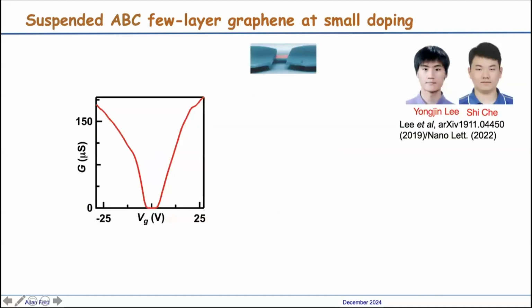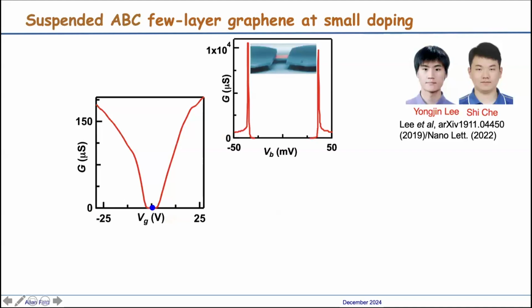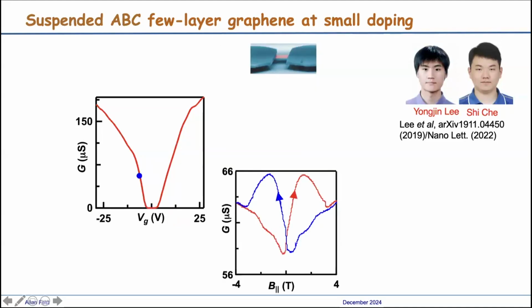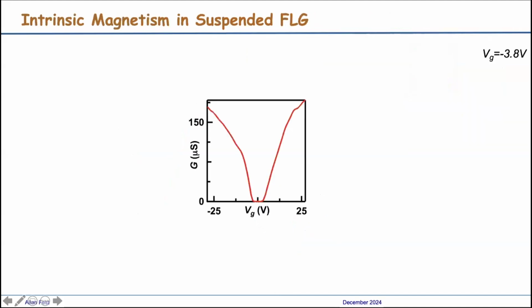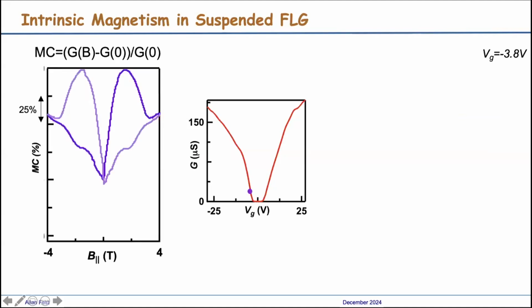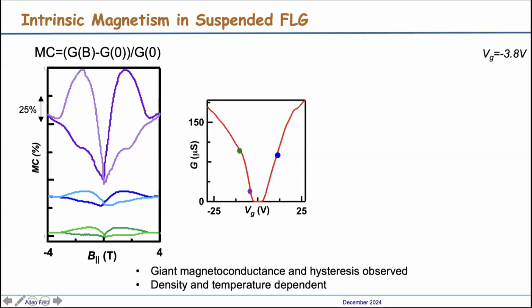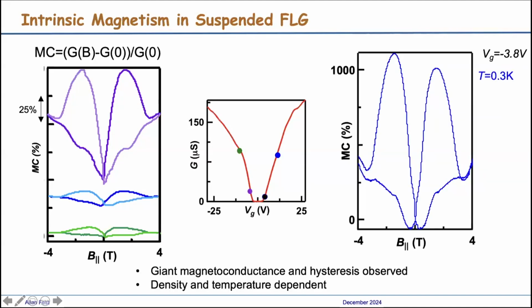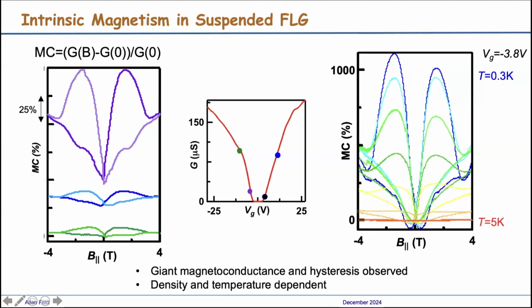Okay, so now if we go to small doping in these suspended devices, at the charge neutrality point we have an insulator. If we dope it slightly, we actually see very prominent magnetic hysteresis. This hysteresis is dependent on density, so it depends on where we go, and it is also temperature dependent. It really disappears at about 5 Kelvin. So this tells us we really have intrinsic magnetism in lightly doped suspended few-layer graphene.